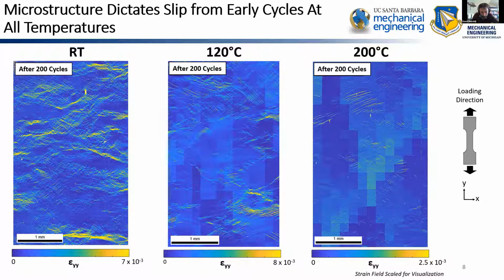There's just one question here from one of the attendees on the chat, which is, why do you say that those localized strains observed at 200 degrees Celsius are not detrimental, though they are not widespread? So the idea is not that they're not detrimental necessarily, but that we're really thinking about this from our load shedding and pile up and these early crack nucleations. And so yes, we could have slip and strain that happens eventually, but these aren't a lot of strain piling up at boundaries that are causing load shedding effects that then cause early crack nucleation.